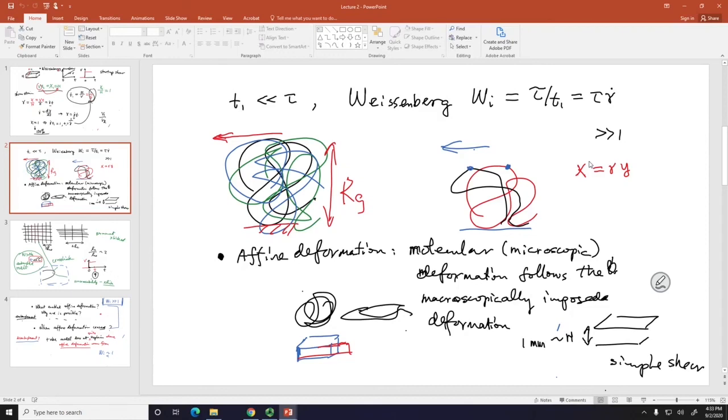Your polymer is really suffering, meaning it has no way to diffuse. It's subjected to this affine deformation, which at some point may break down, and how it will break down was the whole core question in nonlinear rheology that has had no proper answer for a long while.